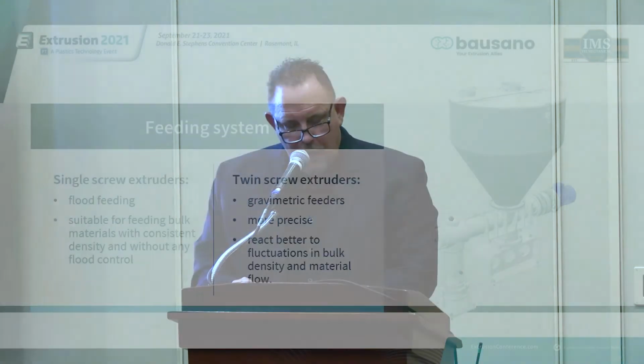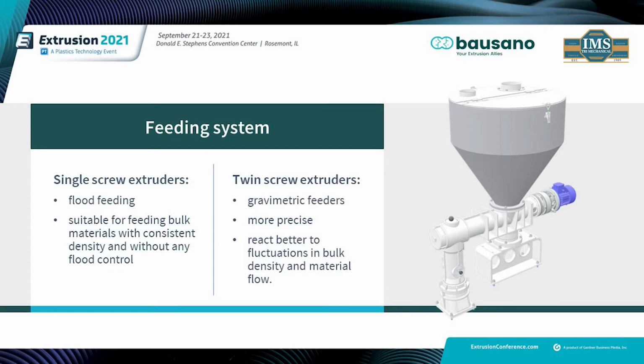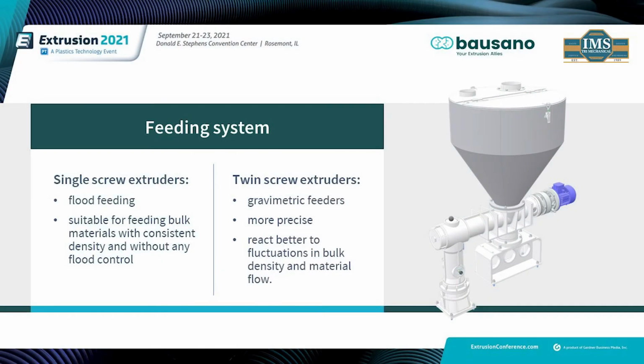An alternative to gravimetric feeders are volumetric feeders. They usually are cheaper but less precise. So for the recycling process, it's better to use gravimetric or loss-in-weight feeders. Single screw extruders are operated primarily using flood feeding, which is only suited for feeding bulk materials with consistent densities. When handling secondary raw materials, the bulk material characteristics can lead to irregularities in plastic flow, also known as surging. In contrast, twin screw extruders typically use gravimetric feeders, which are more precise and can react better to fluctuations in bulk density and material flow.